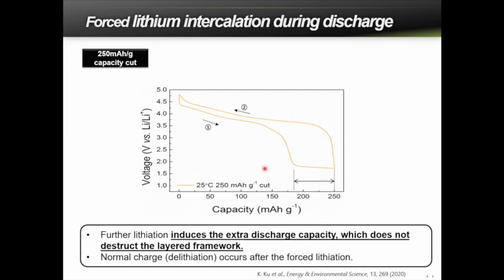And we also could confirm the asymmetric behavior of sluggish discharge and fast charging reaction here. First, we discharged the electrode until the normal voltage cutoff and forced the further intercalation to achieve about 250 milliampere-hours per gram. And it naturally exhibits a voltage plateau lower than 2 volts, which is not usually observed in conventional operation voltage, but is attributable to the tetrahedral lithium occupation in the layered structure.